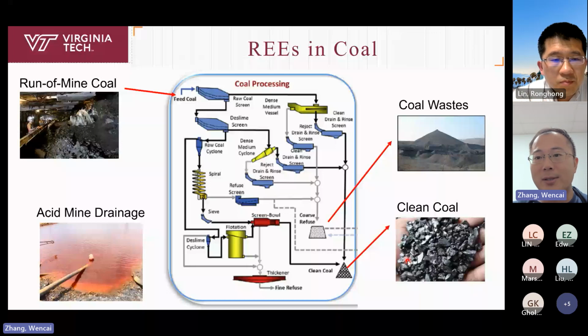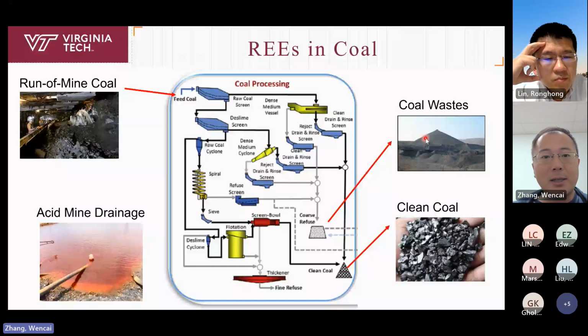Then we also get some coal waste, which we sometimes call coal refuse. This is the high ash content, rock portion of the run-of-mine coal. This is normally rejected, so it is not beneficially used. Also, as you know, there is a lot of pyrite in coal deposits. Once you mine the coal out from underground, the pyrite is exposed to air, oxygen, and moisture. Under these conditions the pyrite is dissolved and generates sulfuric acid. The sulfuric acid reduces the pH of the water. This kind of water we call acid mine drainage.